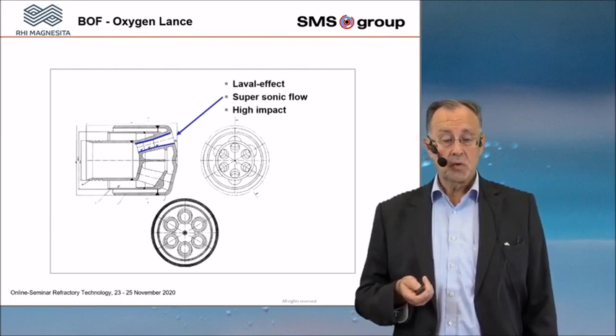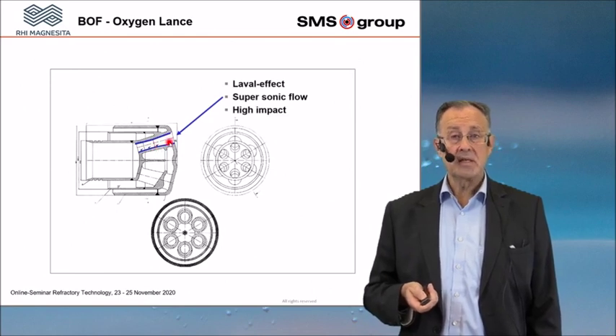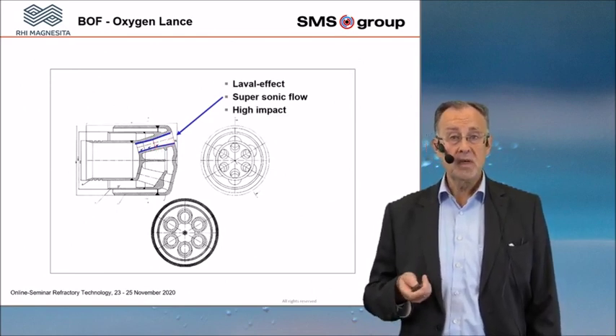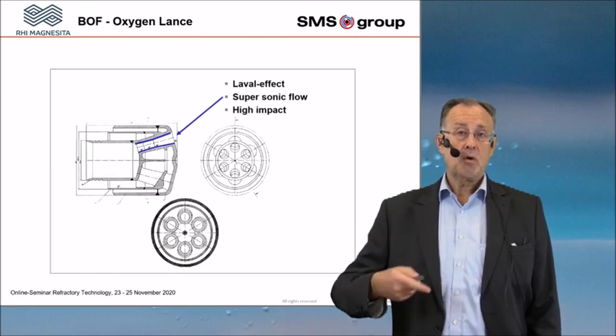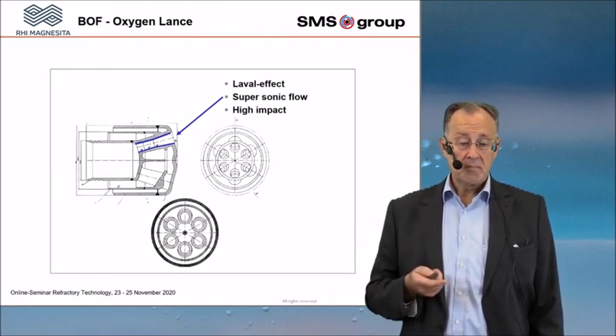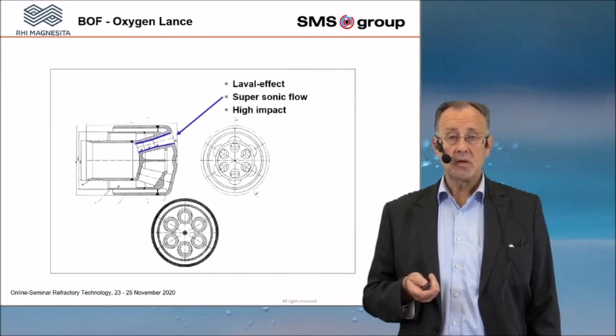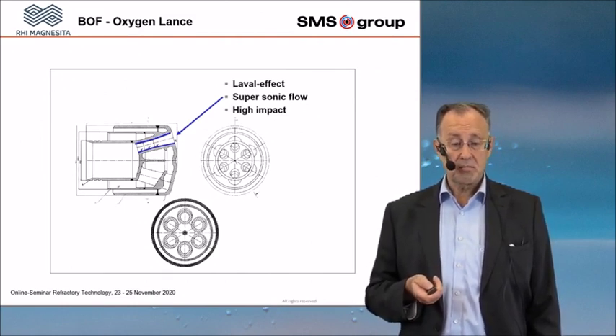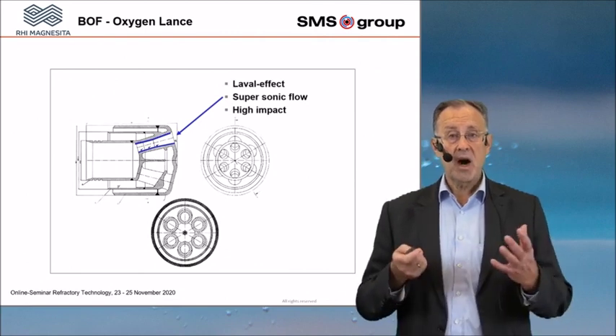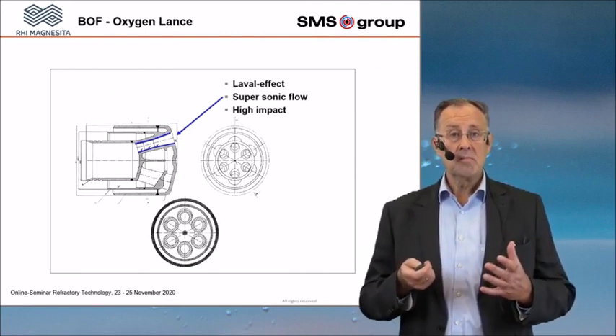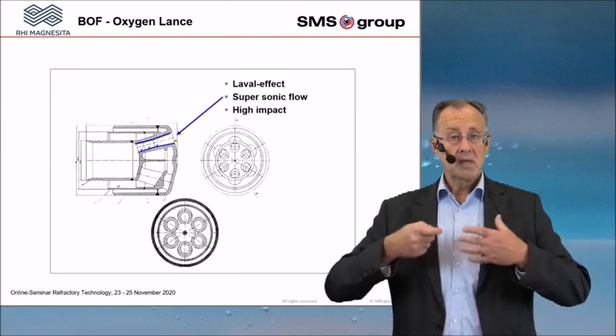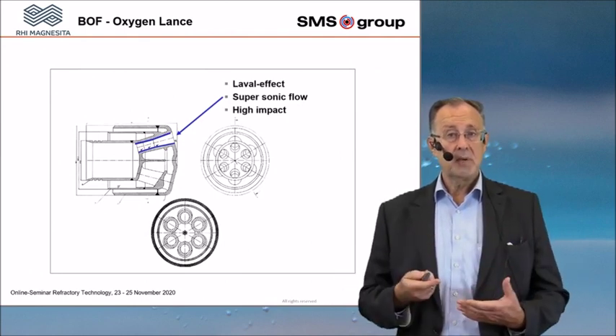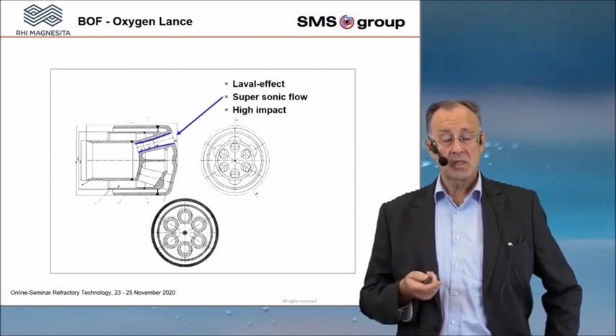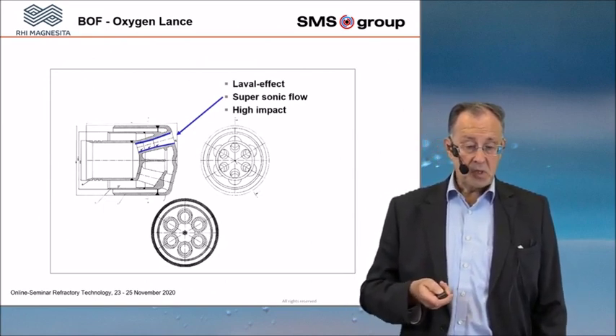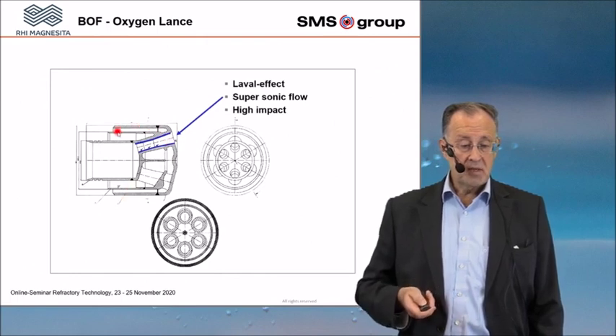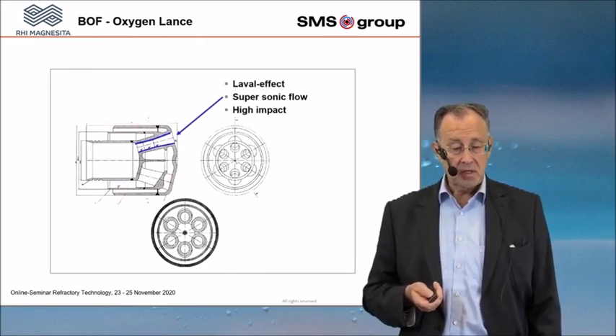This is important to know, because when the oxygen leaves the lance tip, then you have a velocity of 2 to 3 Mach. That means you double or triple the velocity of the oxygen stream coming out of the lance tip. And this is important for the process, because then you have a very high impact of the oxygen stream on the surface of the metal bath, and some part of the oxygen can penetrate the metal bath and do the chemical reactions inside the bath. So everything is water cooled to avoid any damage